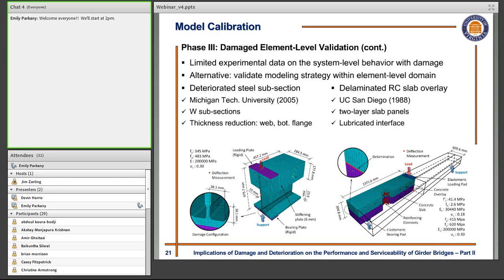In the other case, we were interested to see how delamination would affect the structure, causing it to fail or reduce its functionality. So we selected the experimental investigation performed at the University of California, San Diego on overlaid reinforced concrete slabs, and they had different slabs with different boundary conditions between these two layers and tried to understand how this boundary condition may affect the behavior of these slabs. Among all the specimens that they had, we selected the one that used a bond breaking agent as the lubricant material to simulate the ideal case of delamination.